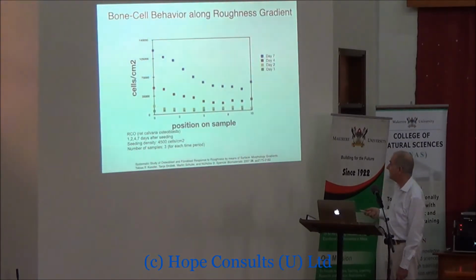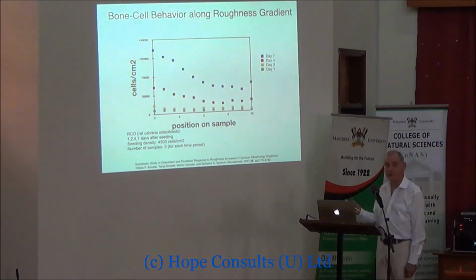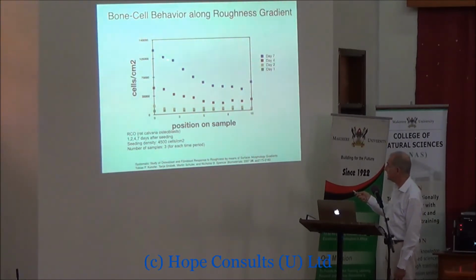And then we put them in a cell culture. These were bone cells from rats, and we looked at the proliferation of these bone cells, how they're reproducing on the surface, and we looked at the effect of the roughness. So as we go along the sample, the roughness is changing, and this shows the number of cells as a function of the time.